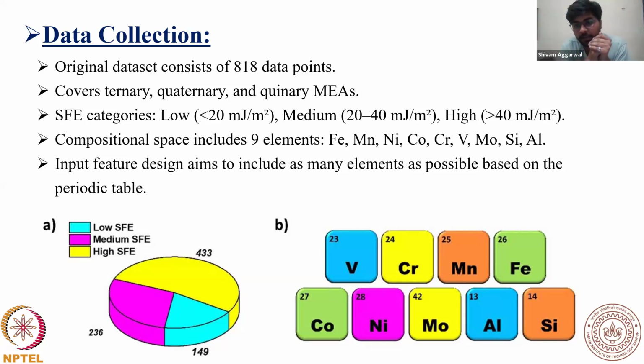We use a very large input compositional space. You can see there are around 149 compositions which have very low stacking fault energy, 236 have medium stacking fault energy, and 433 compositions have very high stacking fault energy. Very high means greater than 40 millijoule, medium means 20 to 40 millijoule, and low means below 20 millijoule per meter square.